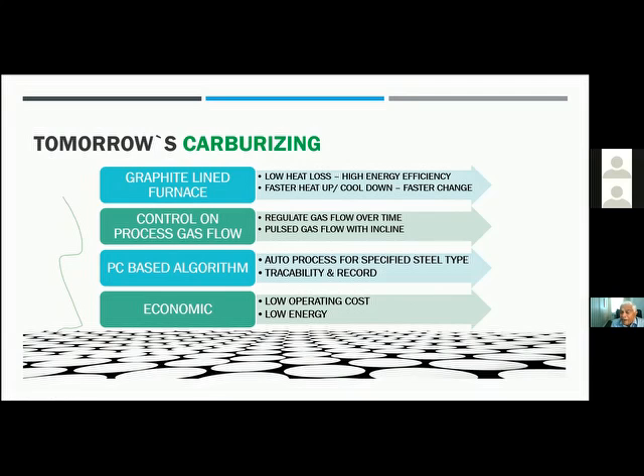These furnaces are all typically graphite-lined furnaces. And graphite is a very low weight, low thermal conductivity material. So it provides very low heat loss at a steady state temperature of 980 or 990 degrees C. In fact, if my memory serves me right, I've been out of it for a while now, at 980 degrees C, a steady state equilibrium vacuum furnace would probably give you somewhere close to 5 kilowatt per square meter thermal heat loss. Compared to a refractory brick, which normally lines a sealed quench furnace or a CGC, would be somewhere around 14 to 15 kilowatt per square meter. We're talking of huge energy savings here, coming naturally out of the materials of construction of tomorrow's carburizing systems.